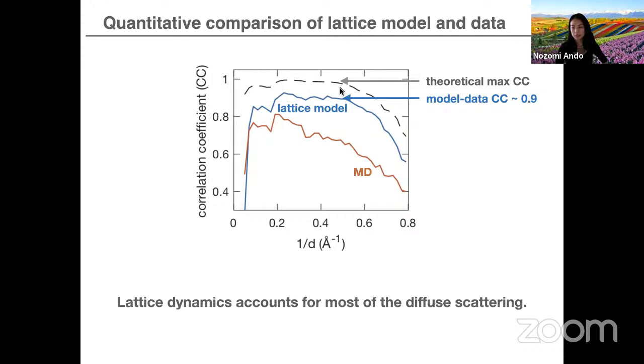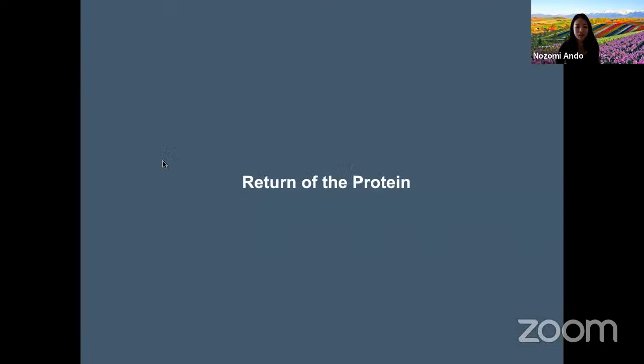Okay, but the fact that it explains the diffuse scattering very well reiterates the fact that lattice dynamics are responsible for a large part of the signal. Okay, so that was the end of episode two. And of course, we set out to look for protein dynamics, but what we instead found was that the dominant signal was due to the lattice dynamics, and we had to look further.